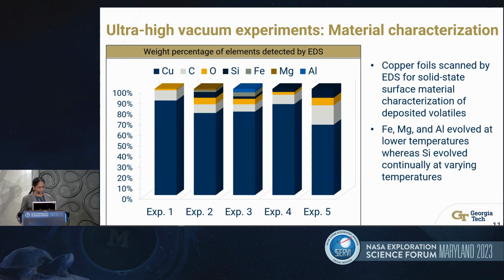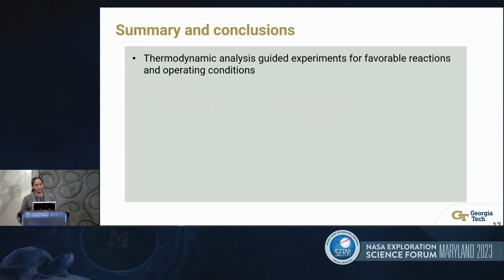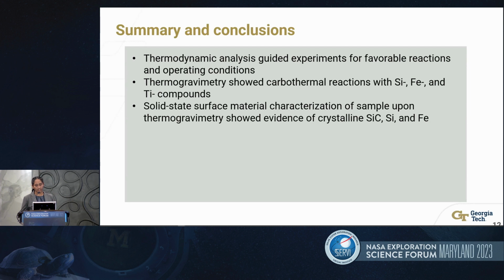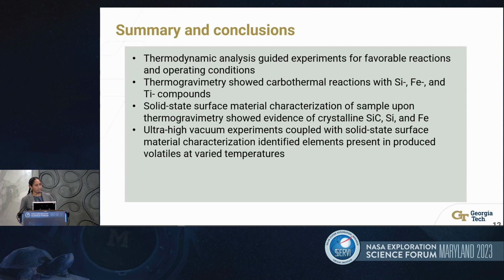different temperatures. So to recap, the thermodynamic analysis guided experiments for favorable reactions and operating conditions, and the TGA showed reactions with silicon, iron, and titanium compounds. And with material characterization, it's shown that crystalline silicon carbide, silicon, and iron were formed. With ultra-high vacuum experiments and subsequent material characterization, solid volatile depositions were identified at varying temperatures.